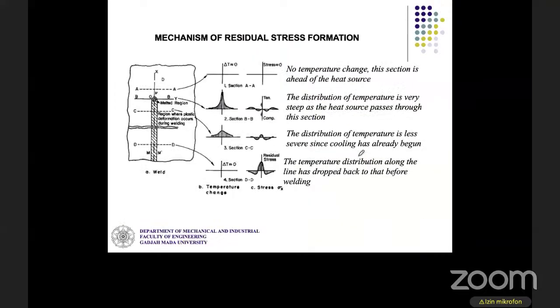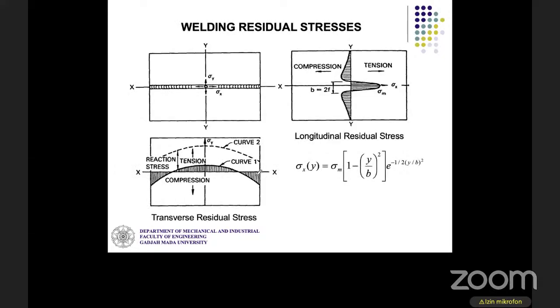And this is the mechanism of residual stress formation. Due to local heating, it produces residual stress where the weld metal and the region near the weld metal reveal tensile residual stress, and to compensate for this, the region away from the weld produces compressive residual stress. And you can see that residual stresses can be divided into two, which are longitudinal residual stress and transverse residual stress. And this longitudinal stress can be represented by this equation.